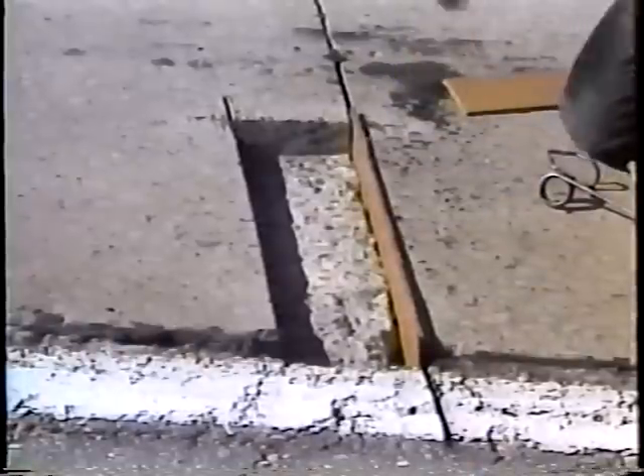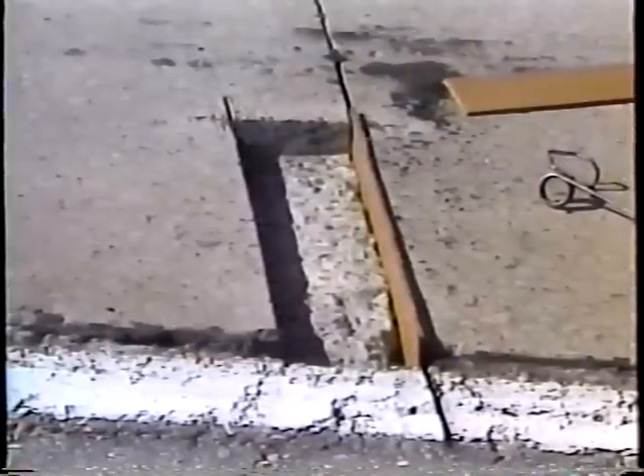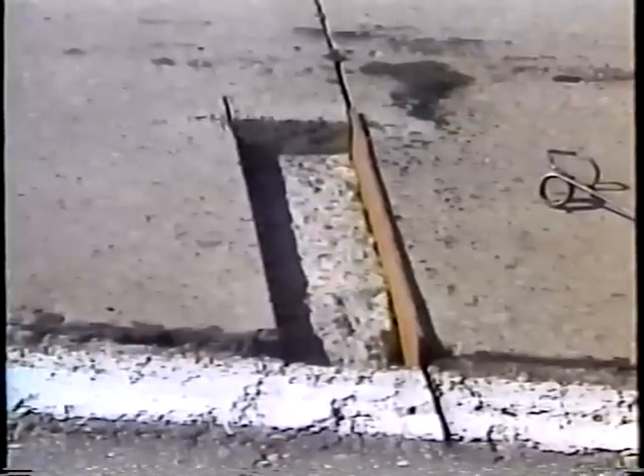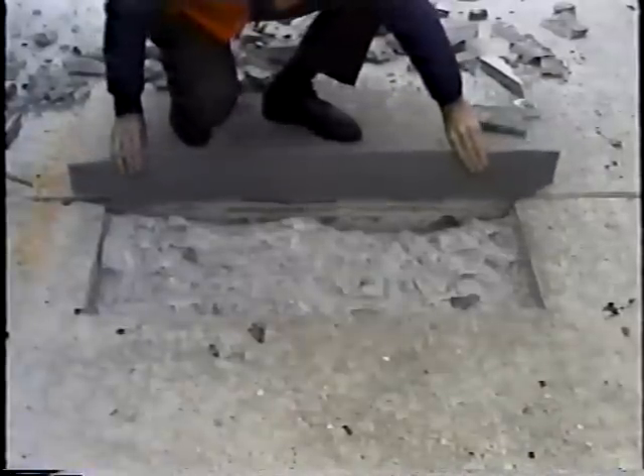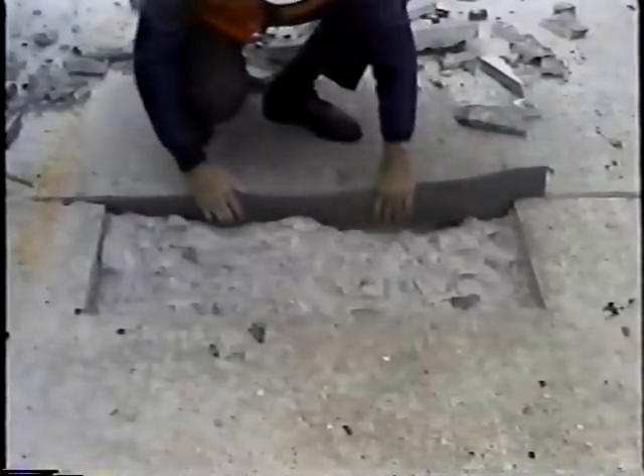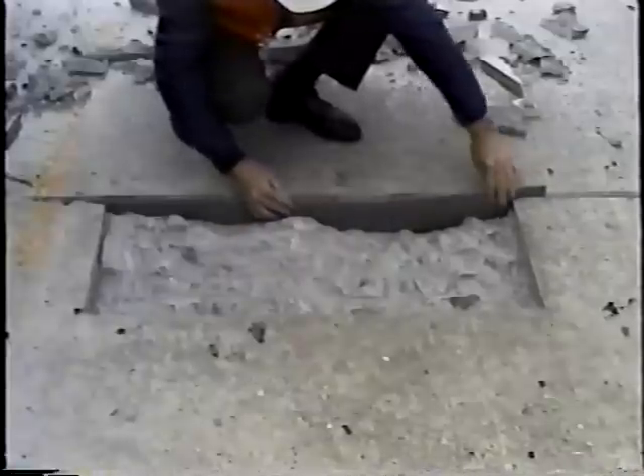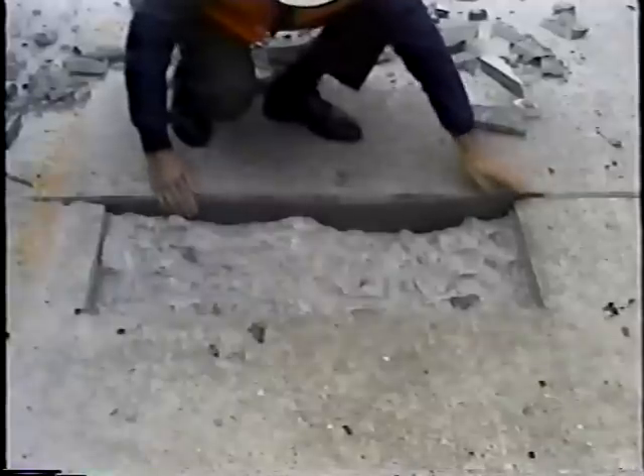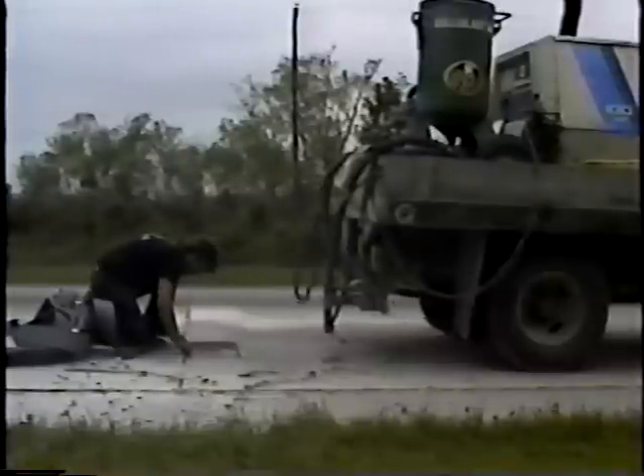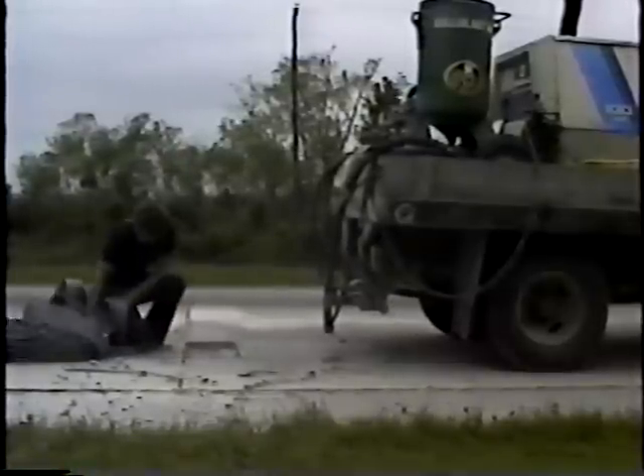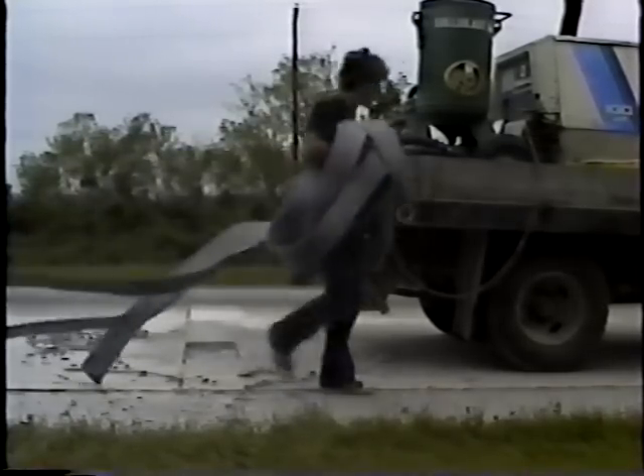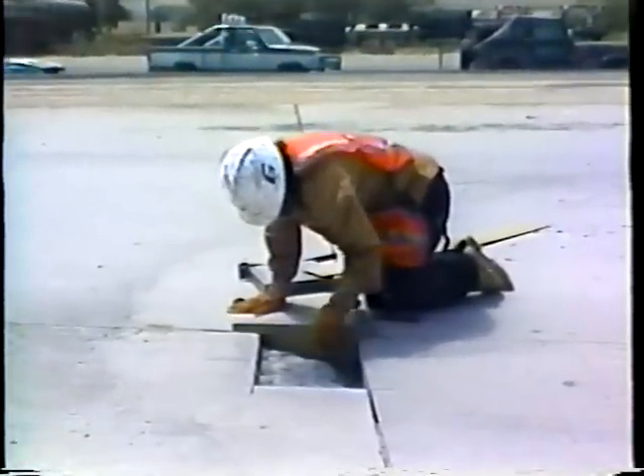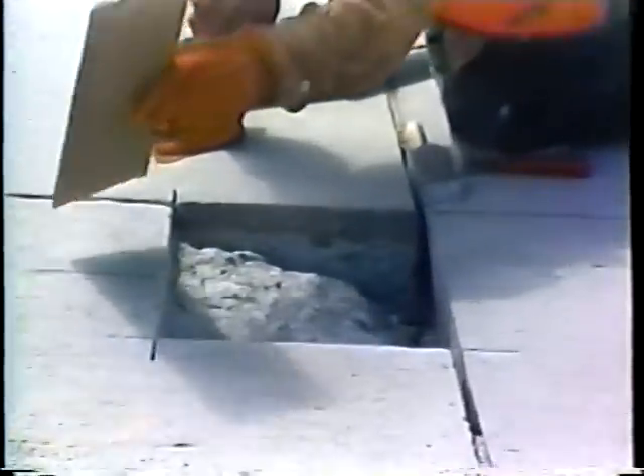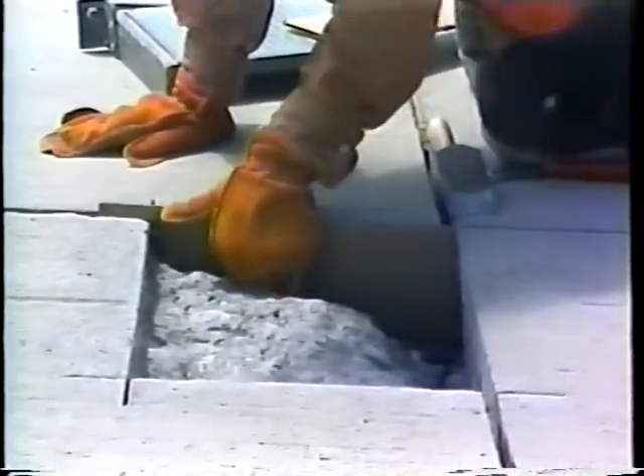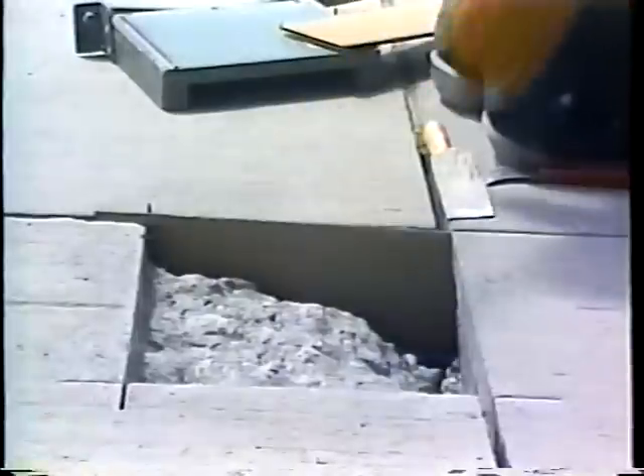Now that's important because the forces created by expansion or differential movement of the adjacent slabs have to be reduced or eliminated. At transverse joints and cracks, the insert has to extend an inch below the bottom of the repair area, and laterally 3 inches beyond the end of the repair area. Sawing may be necessary to obtain these dimensions. Polyethylene, styrofoam, and asphalt impregnated fiberboard are all acceptable inserts. These same materials may be used at longitudinal joints and cracks. When extra side support is desired, stiff polyethylene strips or a thin piece of plywood may be used.